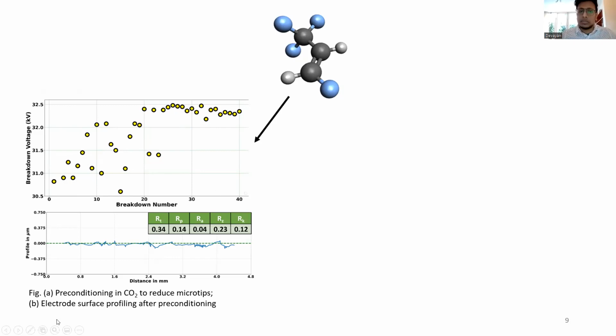Also from the surface profiling itself, you can see the microtips are almost gone. There are some you can't eliminate, but the effect is very low once we do the preconditioning. So how it goes is you have the mirror polished ones, then you do preconditioning in CO2, you measure it, and then we do the shots in HFO.